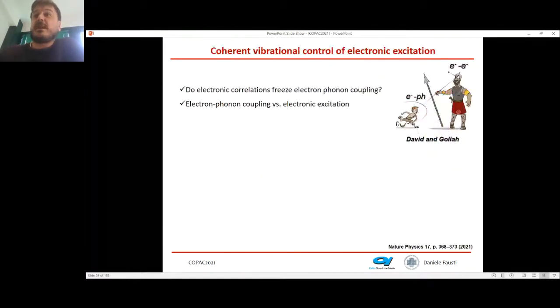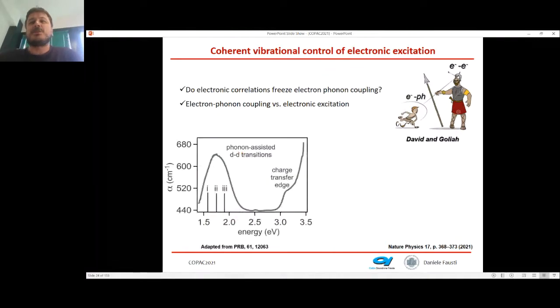And one example of this, which I want to give a little bit more detail on, was published a few weeks ago. It's from my group. It's an idea where we want to use the phonon pump to control electronic excitation. So can we drive a material response remaining in the electronic ground state, so that we don't give thermal disorder to the system? And can we control the electronic excitation just by driving the structure? I like to give this example as David and Goliath, because you want to use a weak interaction, the electron-phonon interaction, to control a strong interaction, the interactions between the electrons.